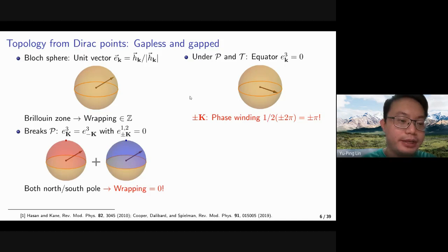We can now try to break the symmetries to gap out the Dirac points. And if we break the inversion, the time reversal symmetry enforces the same sign between the third component at K and minus K. And we know that the plus minus K's are the points in the Brillouin zone where the first and second components vanish. So on the Bloch sphere, they should correspond to the north or south poles.